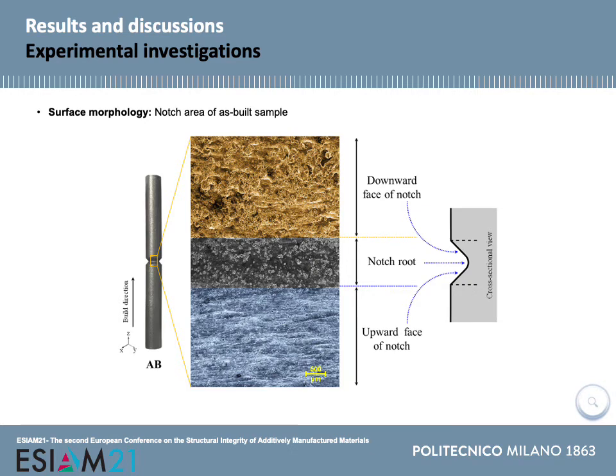Surface morphology of the samples was investigated using SEM. This is the as-built sample. You can see high surface irregularities in different sections of the notch area. In the downward face, the highest irregularities can be seen. This area has the poorest surface quality. Then the notch root, which is followed by the upward face, which has the lowest irregularities in the surface. Unmelted and partially melted powders can be seen easily, as well as the spatters on the notch root.